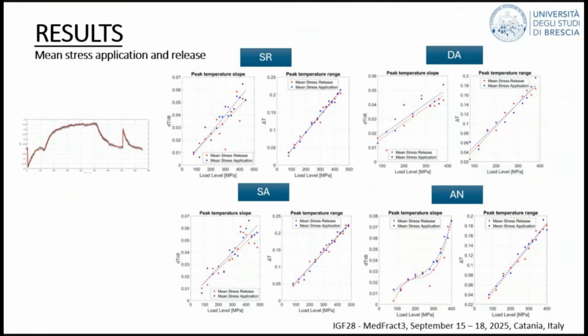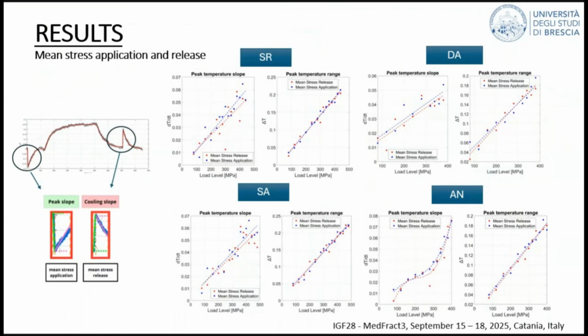So you may remember I mentioned at the beginning that in our test protocol, we applied separately the mean stress and the cyclic part of the loading. So at the beginning and at the end of the test, you have these two spikes where you have essentially a thermoelastic effect. So one question that we wondered was, can we see any difference before and after the application of the cyclic loading between these two peaks? Because the idea is that if you're actually damaging the material, maybe if you compare what happens when you release the stress with what was happening at the beginning of the test, maybe you can get a first indication, a sort of warning, that the material is getting damaged.